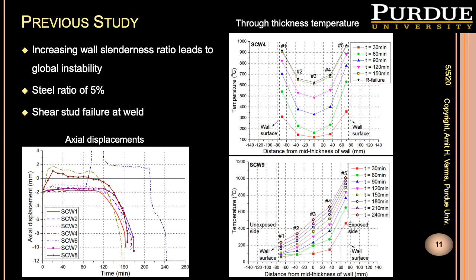This slide summarizes some of the results that were obtained from the tests conducted in China. You're looking at the through-thickness temperature profile for one of the specimens, SCW4. The y-axis is the temperature in degrees Celsius. The x-axis is the distance from the mid-thickness of the wall, where the mid-thickness of the wall is located at 0, and the temperature is increasing to the exterior surface, and the temperature is increasing to the other surface as well. The wall surfaces are where the heating is being applied. We're looking at the temperature profile through the wall cross-section or the wall thickness at 30 minutes all the way up to 150 minutes. And you see how the temperature goes up on the surfaces but lags behind towards the center because of the low thermal conductivity of concrete.